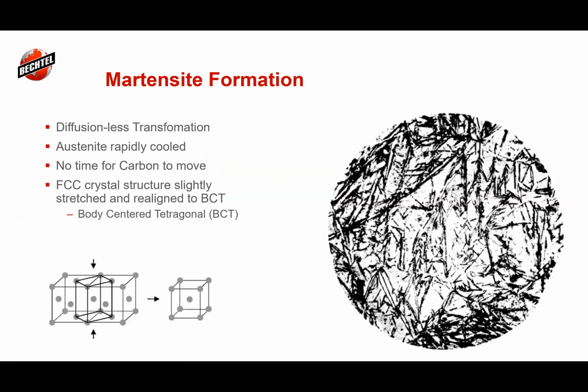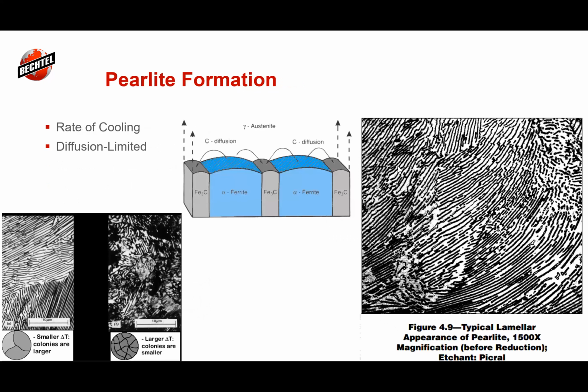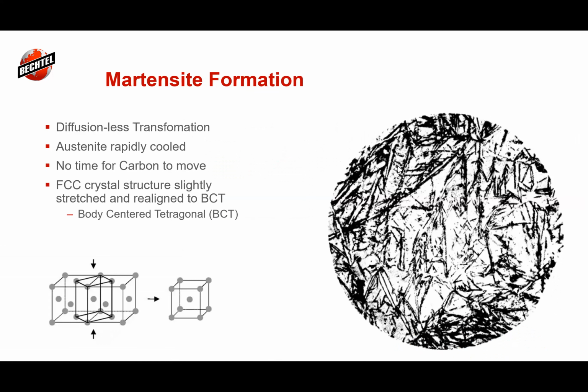And so for the same alloy, we see that the perlite has this nice lath or sort of wavy texture to it. And the martensite's very angular and very acicular. It looks like needles. It looks like ice when it comes to freeze. And that's diffusionless. We didn't give it enough time to move around.